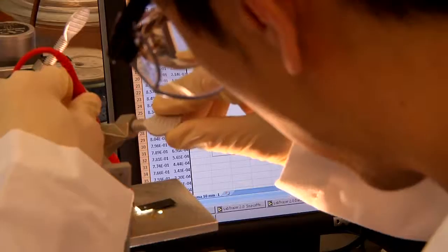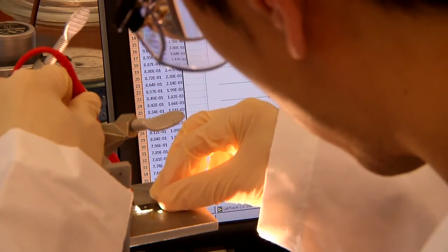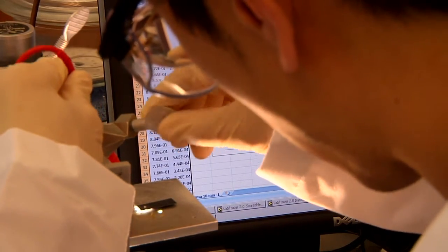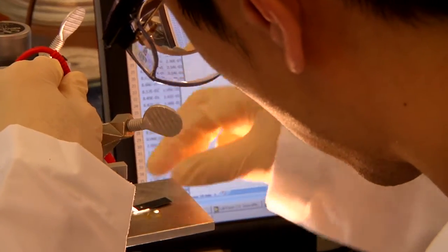Starting at just over 4% efficiency, Lin soon increased that rate to over 5%, and earlier this year, one of his students used an oxygen plasma treatment to increase that gain to 7.37%. Of course, it is not 11% yet as compared to current dye-sensitized solar cells, but this is just our early investigation. I'm very confident someday we will be getting a device with higher efficiency, higher than 11%.